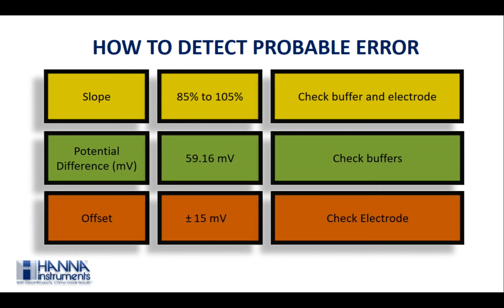So how to detect potential error? Whether the error is in the meter, the electrode, or the buffer. The key to determine error due to calibration is the millivolt of each calibration point. Each and every known standard buffer generates a particular millivolt. Any change in these millivolts will make you understand the potential error. If the millivolt generated in the offset has a large difference, outside the acceptance window, and is carried on to the slope values as well, then there is a deposition on the electrode. If the difference in the pH unit is high, then check your buffers and so on.